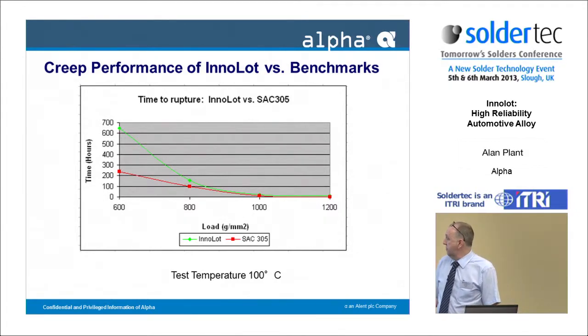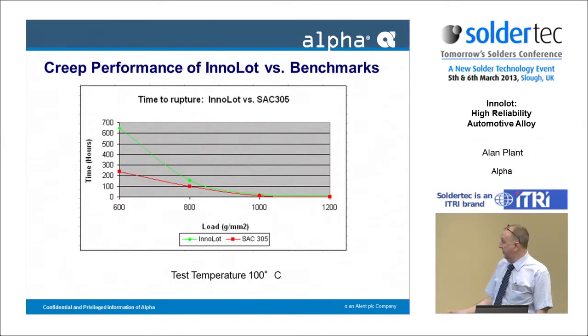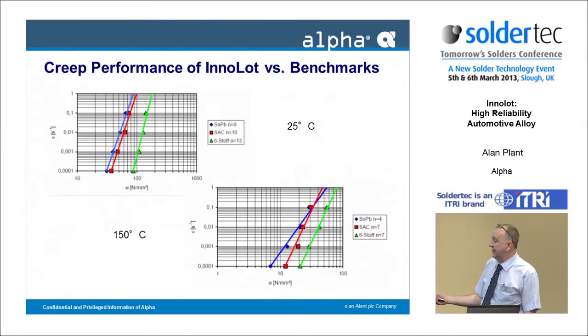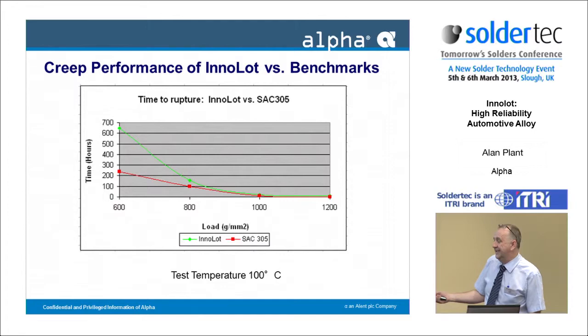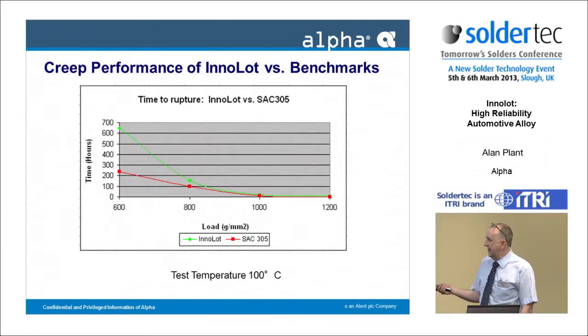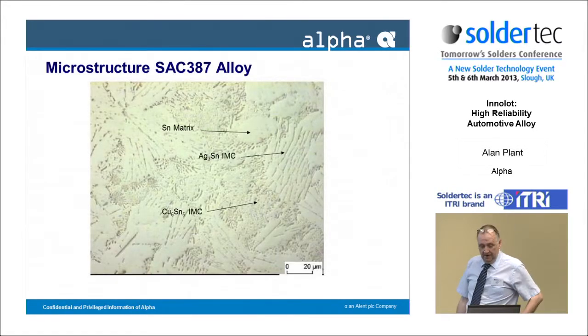Also, here is a creep rupture test at 100 degrees centigrade, but it's really saying the same story. It's a little less subtle than the other tests, but again, it's showing you there is a difference, depending on the creep stress that's applied. That was against the 305 alloy, by the way. Okay, so we've done this, we've made our alloy, what have we done to the microstructure?